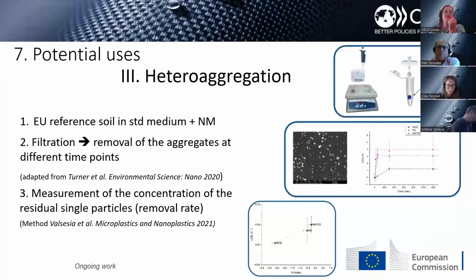We then wanted to study the attachment efficiency of some of the nanomaterials from the ILC using EU reference soil. We adapted the batch test method described in the cited paper, and filtrated the samples to remove aggregates at different time points. We measured the concentration of single particles remaining in the sample, following a method developed in our lab by my colleague Andrea.